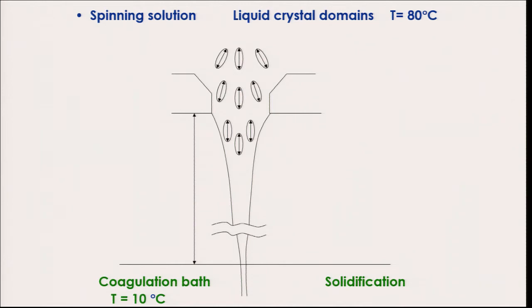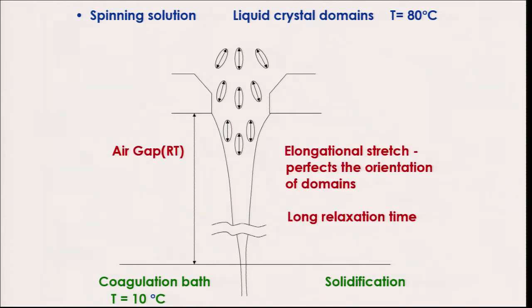So, let us look at the zoomed view of what is happening near the spinneret. If I see here, the spinning solution has liquid crystal domains. That means the oriented structures are forming interactive domains which are all oriented along the flow direction. So, during the flow through the spinneret capillary, they all get further aligned along the fiber direction, and once they are out from the spinneret capillary, due to the elongational stretch that the polymer solution experiences in the air gap, it further perfects the orientation of these domains,